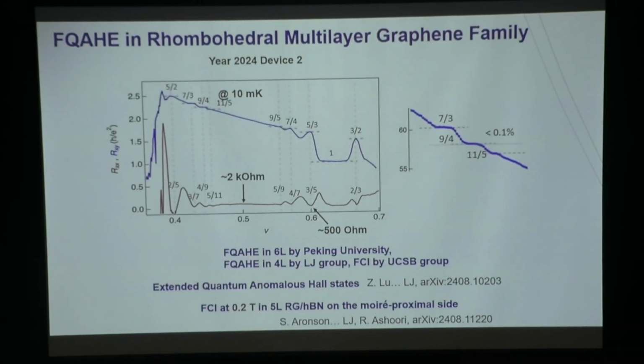Now I can tell you that with some better samples, we're actually able to get to lower electronic temperature with filtering. And if we measure it again, this time at a nominal temperature of 10 millikelvin, while the electronic temperature is probably something like 30 millikelvin, we got a total of 8 fractions. Okay, in addition to the 6 I was showing you, there's 5/9 and 5/11. And the good news is that the residue of Rxx corresponding to these plateaus in Rxy now become much lower. The lowest we can get is probably like 500 ohms, which is more than 1 magnitude smaller, much closer to 0. And this clearly tells us, well, there's nothing wrong with the physics of the anomalous version of fractional quantum Hall. It should be as good as fractional quantum Hall if you improve the sample quality.